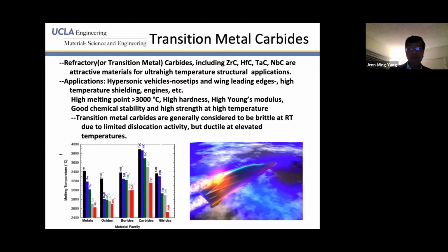But as we know, transition metal carbides are generally considered to be very brittle at room temperature, due to their very limited dislocation activities. But previous investigations have demonstrated that these materials can be ductile at elevated temperatures.